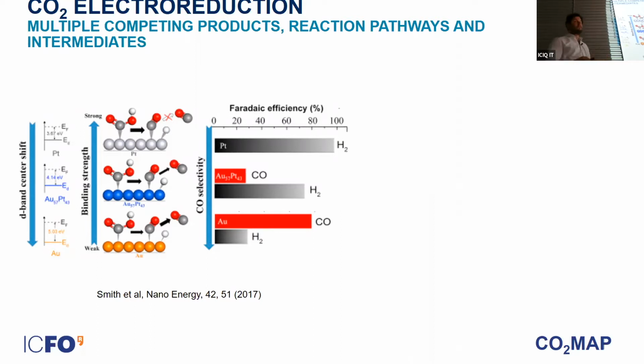So if the binding energy to CO is very high, that means CO molecules want to stay on the substrate as catalytic sites are occupied and they cannot react. So most of what you can do then is only hydrogen. When you have a very low binding energy, the molecules leave and don't couple with each other. So there is always a trade-off, right? You want to have the right binding energy of the metal to the molecules that you want to interact.